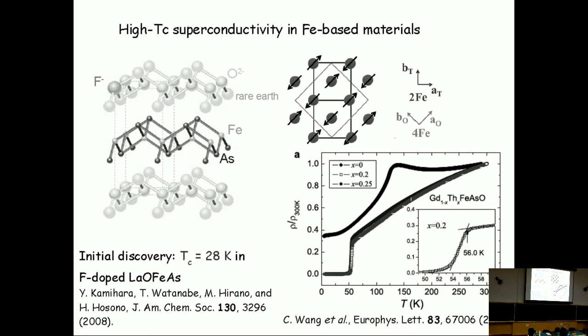Let me start making a general introduction about these systems here. The iron-based superconductors. Originally, superconductivity in these systems was discovered in the fluorine-doped lanthanum oxygen iron arsenic, with Tc equal to 28 Kelvin. And the crystal structure of these materials can be seen as composed of layers of iron arsenic, where each iron is surrounded by a tetrahedron of arsenics, making a layer. And these layers are sandwiched between rare earth layers and also oxygen layers, where the fluorine can be doped into.